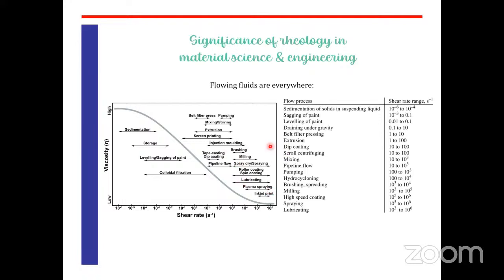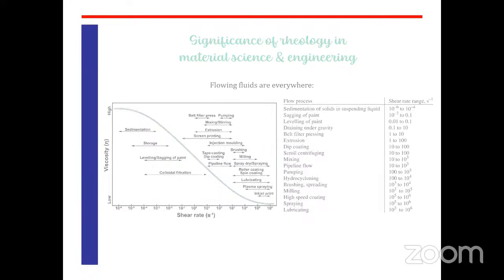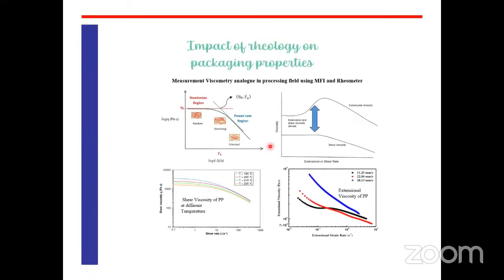But this is the basic graph that we get from any kind of rheometry, rheological measurements, right? So again, this is the same thing. We get MFI and rheometer data that you can easily get. This is the shear viscosity at different temperatures of polypropylene. As you can see, if the temperature is increasing, you are getting a reduction in your viscosity. If you get a reduction in your viscosity, then flow will be more.